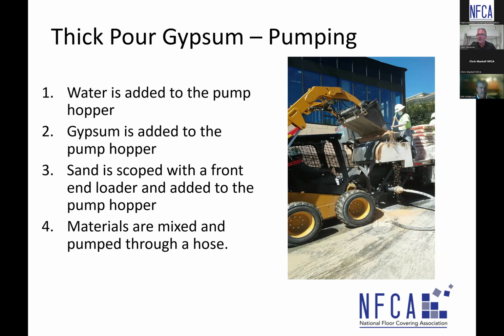You can see the bags of pure gypsum behind the guy in the picture there. You can see a bobcat there with a front end scoop. And there are different ratios depending on the size scoop that the bobcat has. One scoop of sand equals X amount of gypsum, X amount of bags of gypsum. And then certainly there's a water ratio to get the right consistency.